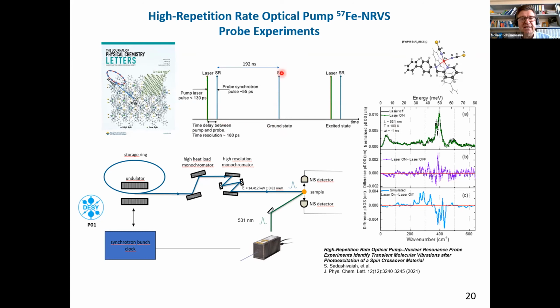And when the next synchrotron bunch came, we didn't apply the laser flash, so that was the reference. And then the next came and we measured that also. And here you see the two traces with laser on, which means probing here, and laser off, which means probing here, the ground state. And this is the difference, experimental difference. This is a simulation based on a model, which I show you in a second. I should mention that was done with a picosecond laser, and we can also do that now with femtosecond lasers. The sample was cooled with the cryostream, which you normally use in crystallography beamlines.